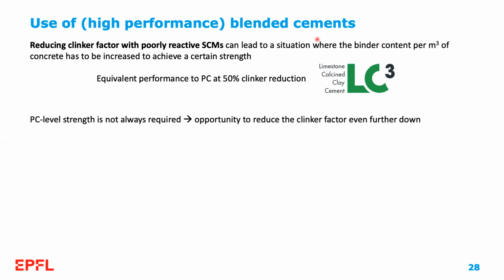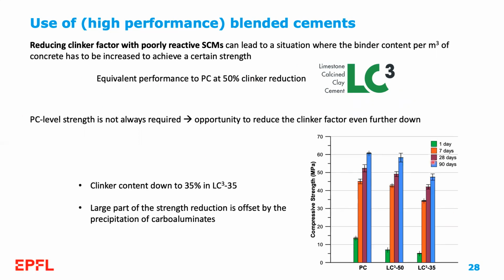So this is why, again, LC3 is so special, because it offers equivalent performance to PC at 50% clinker replacement. But PC level strength is not always required, and this is an opportunity to reduce the clinker factor even further down. We did trials with what we call LC335 with 35% clinker, where we don't achieve the same strength level of PC as we do with LC350, but we still achieve something that is above 40 megapascals at 28 days. A large part of the strength reduction is offset by the precipitation of carboaluminates in the system.